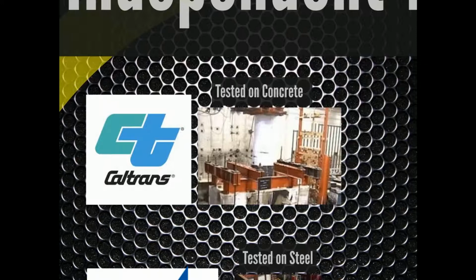One of the first third-party studies that was performed was by Caltrans, and they tested it on a concrete bridge column. Basically, they wanted to find out if a bridge was damaged severely in an earthquake, including rupturing of the longitudinal rebar, could we install PileMedic onto that column and then retest it after the repair and see if we brought that column back to the original capacity. And the test was successful. We were able to exceed the original capacity and actually reached the limit of the press.